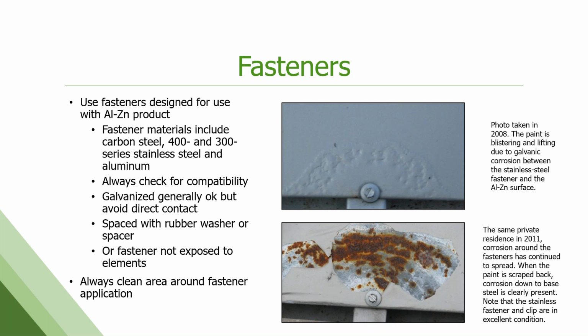So what we have here is galvanic corrosion. The top picture was taken in 2008. This had been installed for about 3 years at this point. Came in as a paint failure. My paint is blistering, my paint is bad. That's how the claim came in. Went out there and inspected it, and that fastener and this clip that's holding the gutter in place here is stainless. This house is about 300 feet off the surf break outside of San Diego, so highly corrosive environment.